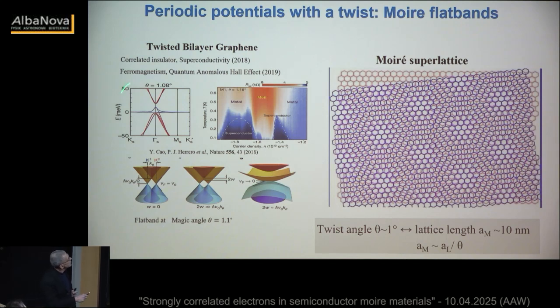Now, the first experiment on this was by Pablo Jarillo-Herrero at MIT, where, following MacDonald's proposal, he showed something really remarkable. He starts from graphene, which has massless electrons, the worst you can imagine in some sense, because they have a completely linear dispersion. And when you go to a twist angle of about 1 degree, 1.08, you find a completely flat band appearing in between, the remnant of the linear dispersion. And then when they did the transport measurements, you see the similarity of this phase diagram to what I showed for the cuprates, the temperature versus the carrier density.